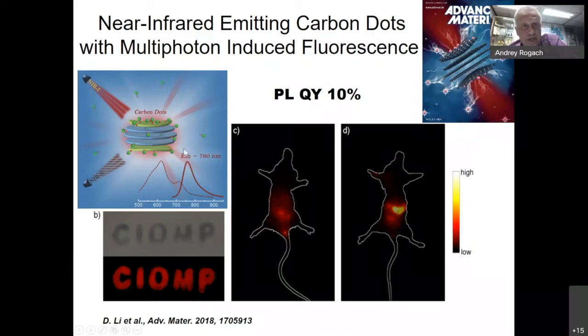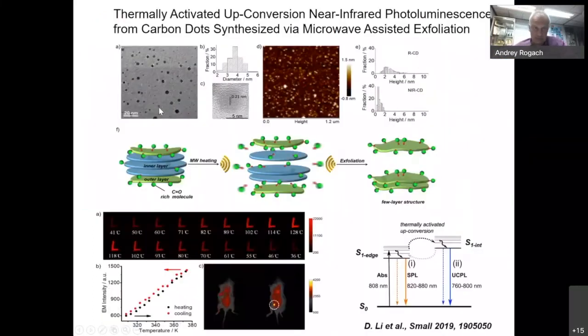And how we did it? Essentially, we took carbon dots and we exfoliated them by so-called microwave-assisted exfoliation. Because these spherical carbon dots, actually, they have few layers of graphene. You can think about that way. And if we treat them using microwave, they will exfoliate. They will go apart a little bit. Or they can be evenly exfoliated completely. In order to do so, we make them emit infrared light. And this is exactly what we wanted to achieve by this treatment.